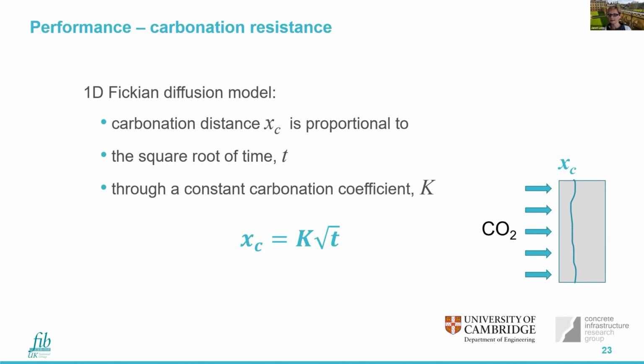And in the sense of a progression of a carbonation front, again, if we fixed time, a lower K would mean a lower XC, hence a smaller carbonation front. A higher K means a higher XC, hence a carbonation front that has progressed further into the structure. So generally, a lower K is better carbonation resistance, higher K is poorer carbonation resistance.